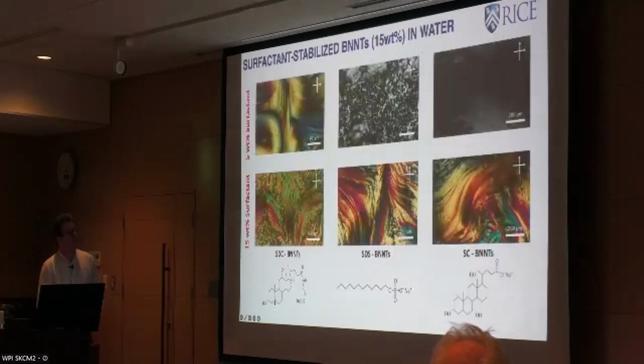So we see the typical dependence of color on the nematic thickness. At some point, it gets hard to fill the capillaries at high concentration. And the tactoids in higher viscosity samples actually remain even after sonication, and that gives darker and unexpected birefringence. But right now, this is also very exploratory.